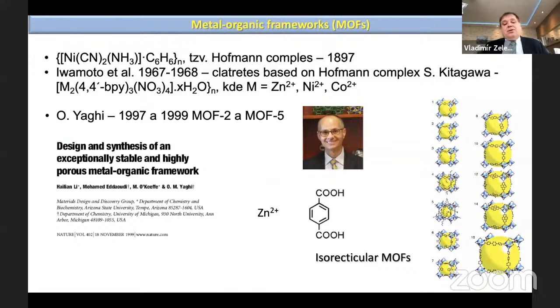Metal organic frameworks we are also studying and dealing with. They were discovered in 1999 by Omar Yaghi from the United States, and he prepared porous zinc terephthalate. So he combined zinc ion with 1,4-benzene dicarboxylic acid, terephthalic acid, and he prepared a porous structure. And he also managed to change terephthalic acid to other dicarboxylic acids, and he prepared a series of MOFs, so-called isoreticular MOFs, which have the same symmetry but different pore volumes. And you can increase pore volume, and these yellow spheres in the picture show the volume which is available for gas adsorption in these materials.